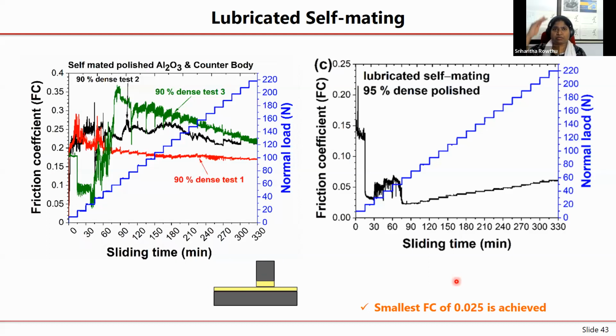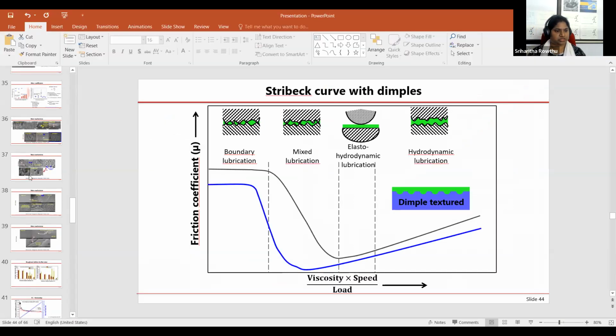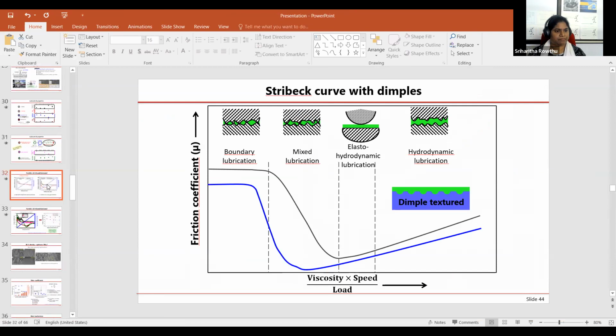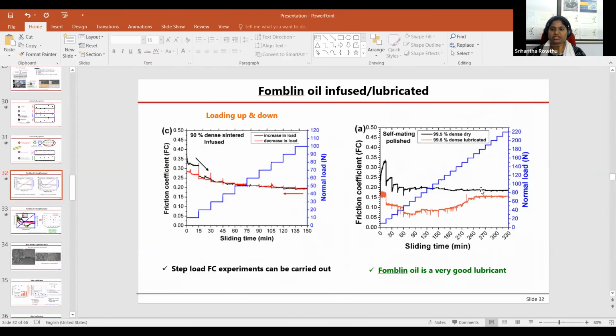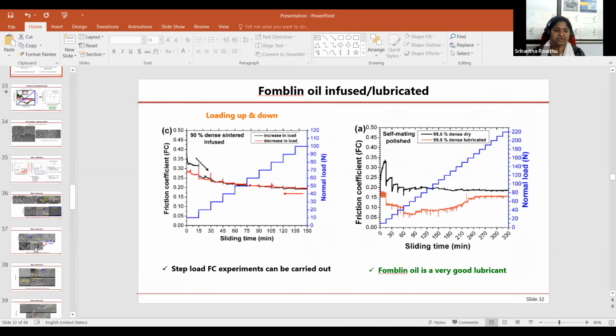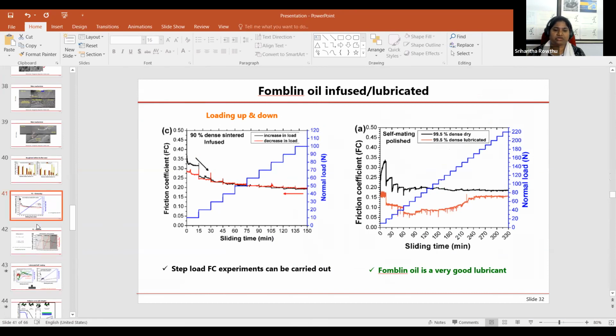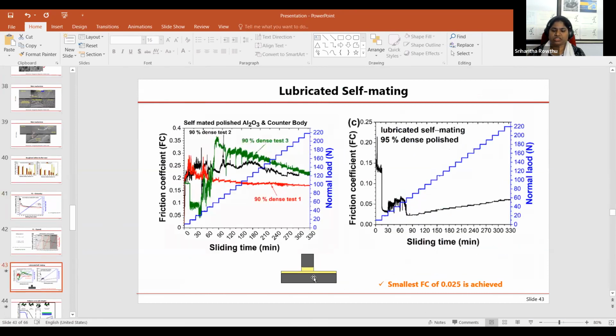So remember, your fully dense alumina sample was having a very high value. I don't recall exactly, let me check. Yes, your fully dense alumina sample was having around 0.2, but now with the lubricated situation, we are able to have 0.025. So almost 1 order of magnitude smaller friction coefficient was achieved when both the samples were coated.